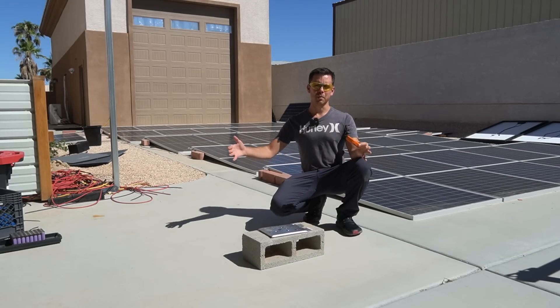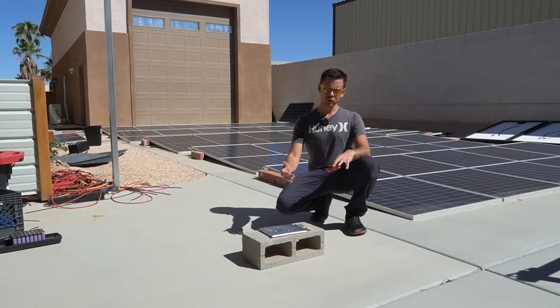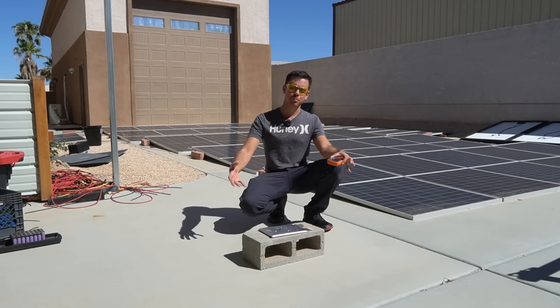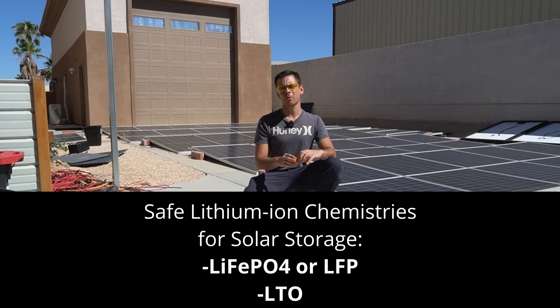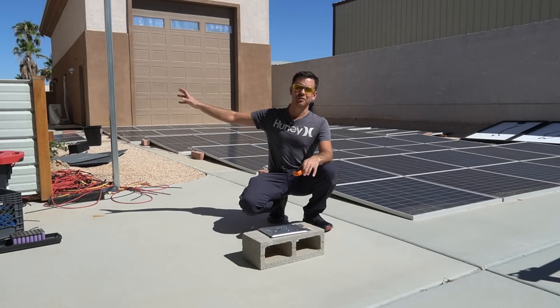In some ways it's safer than a big pile of wood. Batteries are still very dangerous, but lithium iron phosphate is a lot safer than the alternatives. The only other lithium-ion chemistry that's safer than lithium iron phosphate is lithium titanate oxide (LTO), and LTO is incredible — you can drill into it, you can cut it in half, and nothing will happen at all. Pretty much any other lithium-ion chemistry that has cobalt is going to react in a massive ball of flames. Lithium iron phosphate and lithium titanate oxide are the best ones out there, and on this DIY Solar channel we only use those safe chemistries — because we want to deal with this, not with a fireball inferno. It is a world of a difference.